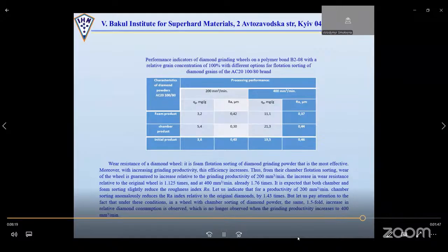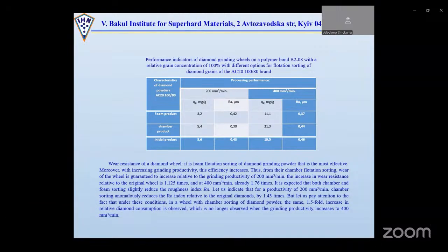That is, for foam flotation sorted diamond powders, the main factor in increasing wear resistance is an increase in their strength index, but for chamber flotation sorted diamond powders, the main factor is the proportion of impurities in them. For wear resistance of a diamond, it is foam flotation sorting of diamond grinding powder that is the most effective. Moreover, with increasing grinding productivity, this efficiency increases.